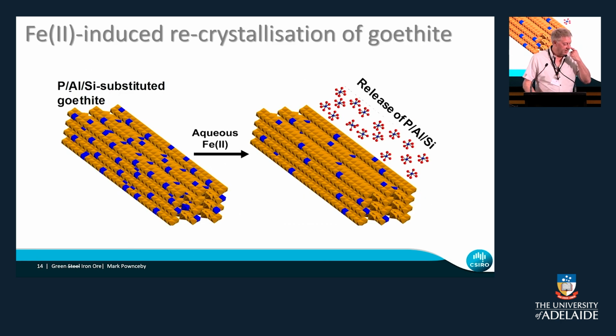The other one we're working on is similar to a leaching method, and this relies on the fact that we know that a lot of the goethite is highly contaminated by elements that are actually in the structure of the goethite. Aluminium will substitute into goethite. It's actually a direct replacement for iron, so that is a big issue, and you can get up to 15 mol% aluminium in goethite. Phosphorus is an interesting one where no one knows the mechanism of phosphorus incorporation, but it's always in there. We're trying to work that out. We think you can actually substitute a small amount in.